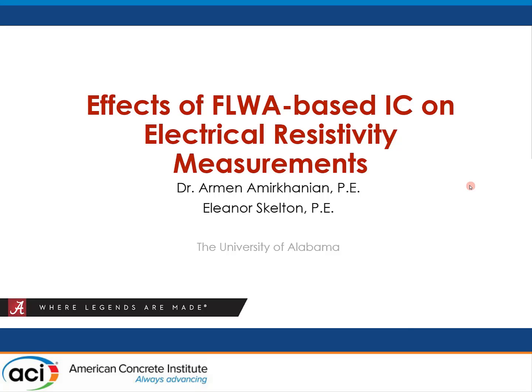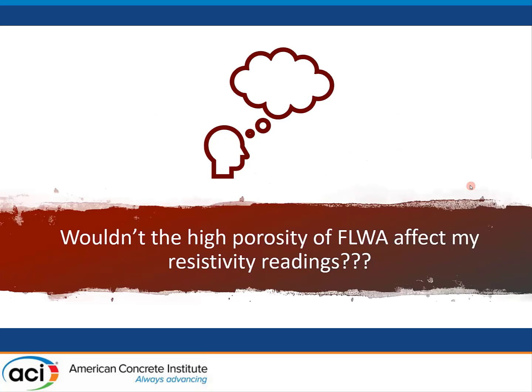And what we're going to talk about today is just a thought I had as I was looking through some of the old resistivity data over the past decades and thinking about, well, if we were measuring resistivity on an internally cured, let's say, bridge deck, wouldn't the high porosity of the lightweight aggregate somehow affect the resistivity readings? Not necessarily make it worse or better, because that's not really a good way to describe it, but the porosity inside the aggregate itself should, in theory, affect the resistivity readings.